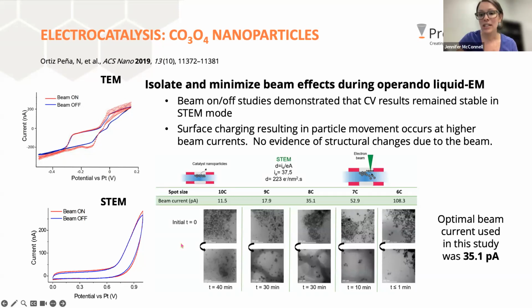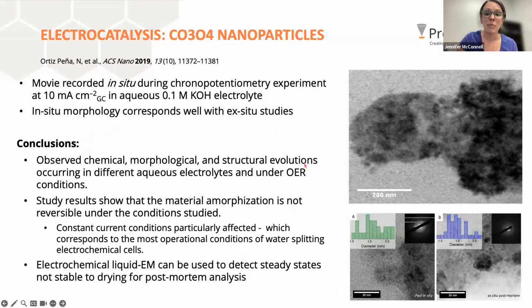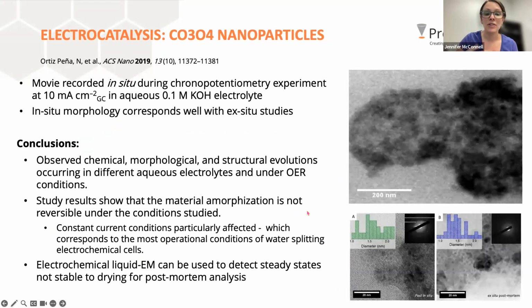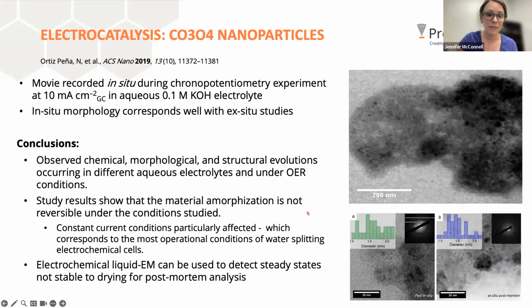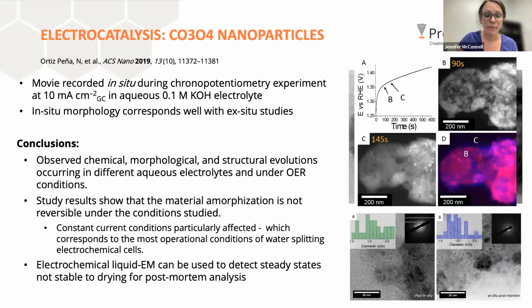Again, they were trying to understand the morphological changes over time. They noticed that there is an amorphization that occurs in these particles as they undergo cycling, and you can see that change in structure here. And you can see the cycling they did. I think they did chronopotentiometry in this experiment. As time went on and the potential was run and continued, you can see the changes in the structure over time. So B, C, and then you've got an overlay of the two here.